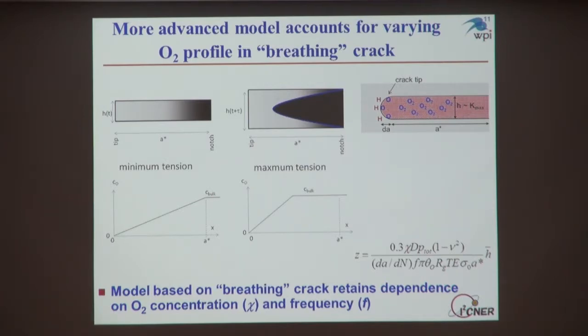And essentially what he's showing here is that at the minimum tension position, so at the position where the crack is closed the most, we might have an oxygen distribution profile that looks like this. And the shading is just supposed to be representing the different oxygen concentrations. So this is the highest oxygen concentration, this is the lowest.